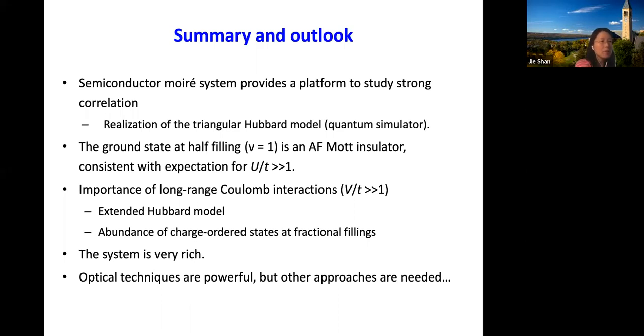I would like to answer this question from Shen Fan. Does the BN spacer affect the Moire effect for WS2, WSe2? The short answer is no. The hBN is random, and the lattice mismatch between hBN and the TMDs is huge, so we don't expect any Moire effect either.